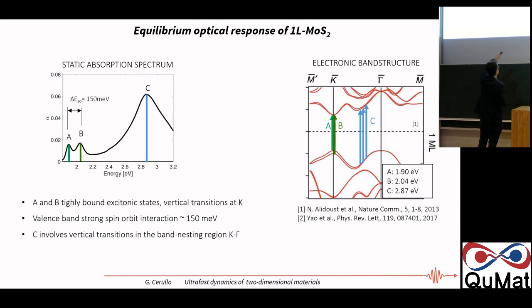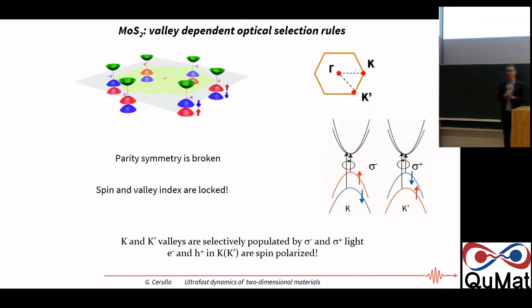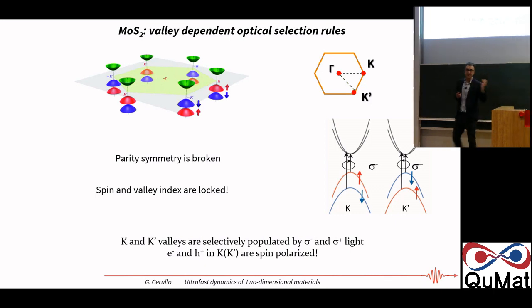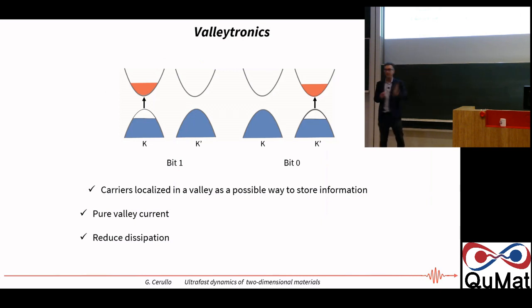And then you have a third transition, which is the C exciton, which comes from vertical transitions in the gamma-K band nesting region. Now, another remarkable property of this material is its valley-dependent selection rule. Since the parity symmetry in this material is broken, you have a locking of spin and valley index, meaning that you can selectively populate the K or the K prime valley by circularly polarized light. And so you can address selectively one of these valleys and you can create electrons and holes that are spin polarized. So in addition to the electron spin degree of freedom, now you also have the valley degree of freedom. You can, in a way, control in which valley you put your carriers.